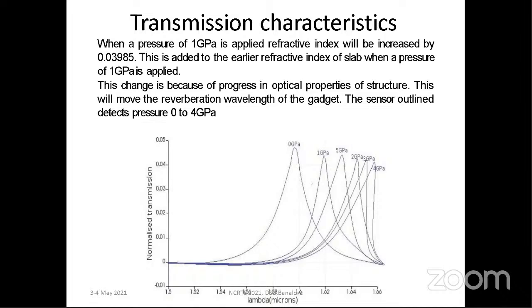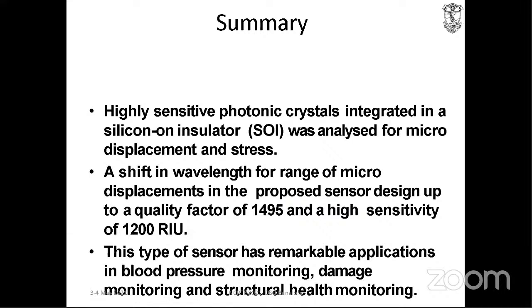Here only. You can see applied pressure is 4 gigapascal, 3 gigapascal, 2 gigapascal, 5 gigapascal, 1 gigapascal, 0 gigapascal. So depending upon the applied pressure, you are going to get different shift in wavelength because there will be change in refractive index. Next. So what we have seen in this one is a shift in the wavelength for micro displacements in the proposed sensor, with a quality factor of 1495 and a high sensitivity factor of 1200 RIU. What I would like to stress here is, if you are using a resonator to get high sensitivity, you should have high Q. Q means quality factor. Okay, next.